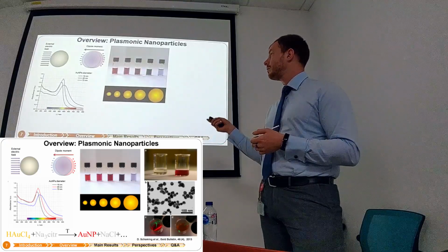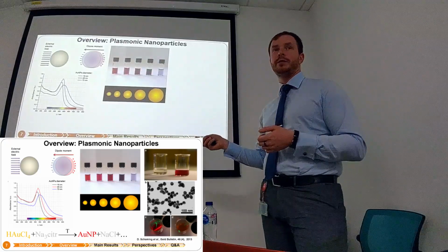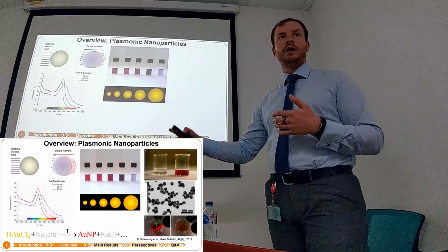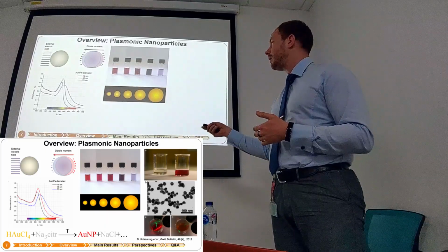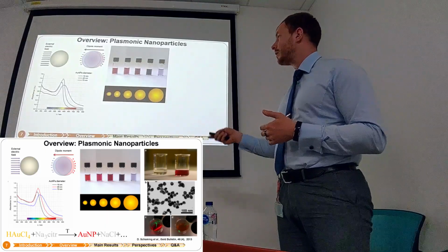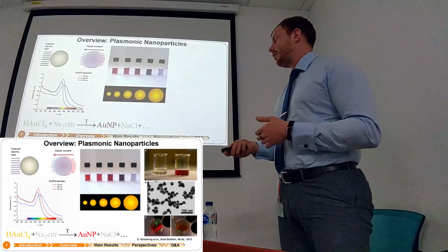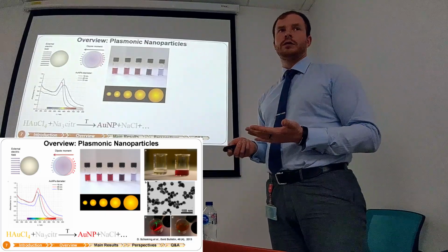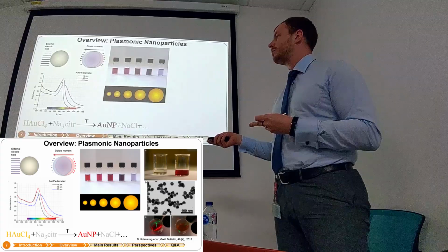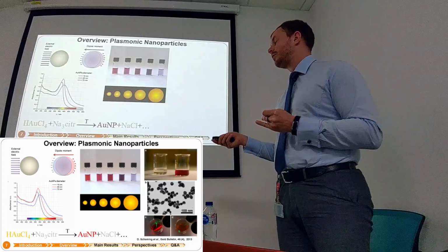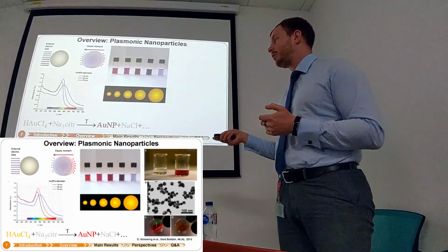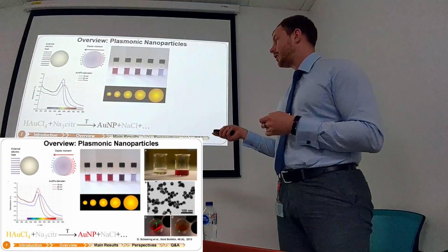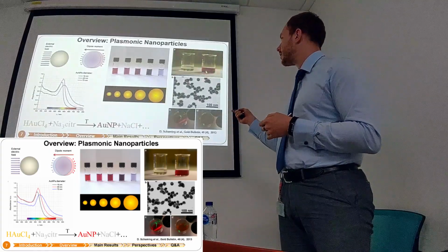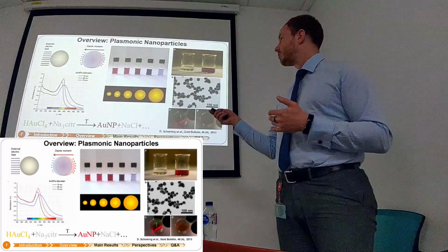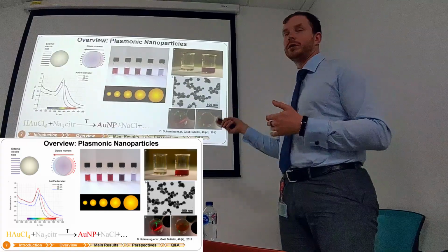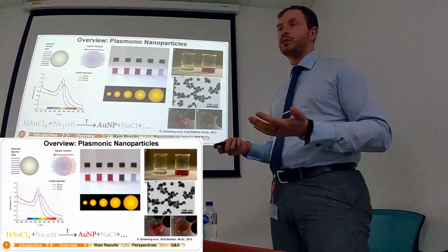This is pretty clearly visible when you synthesize different sizes of nanoparticles, and different sizes of nanoparticles give you different colors. We used a pretty common synthesis, so nothing special. We took a source of gold, we used some reducing agent, heated it up, and we finished with such a nice red. So we started with yellow, but we finished with a red solution of nanoparticles.